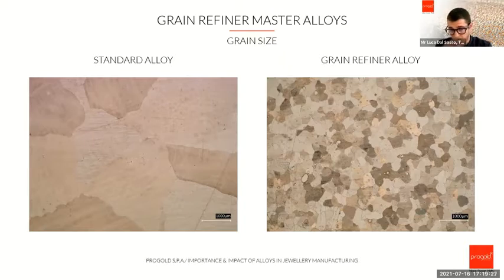What does the grain refining master alloy do in particular to help the alloy have this finer grain microstructure? Basically, it helps to start the solidification from a larger number of spots. So many spots in which the solidification of the metal begins allows a larger quantity of grains. And so a larger quantity of grains in the same area means that they are going to be smaller. So basically, this is the quick explanation of why and how the grain refining master alloy acts in the metal.